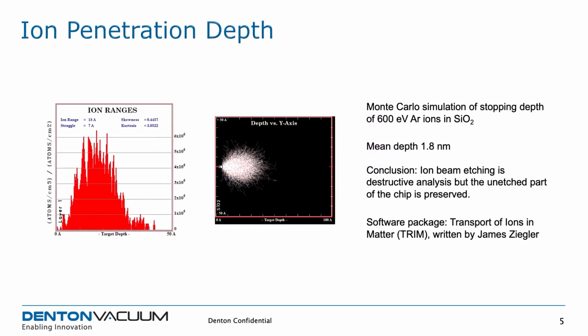So one aspect of ion beam etching compared to other methods is that the ion penetration depth is actually not very deep. If you're used to plasma FIB or some other techniques that use ions in the range of 10 to 30 kilo electron volts, this is actually quite low. So a typical ion energy we use is 600 electron volts. And this is a simulation done using the TRIM software, which shows that for argon ions of 600 electron volts into a target of silicon dioxide, they only penetrate a mean depth of around 2 nanometers, although some can go as high as 4 nanometers. So that's very thin compared to the thickness of layers, even at advanced node, until you get right down to the device.